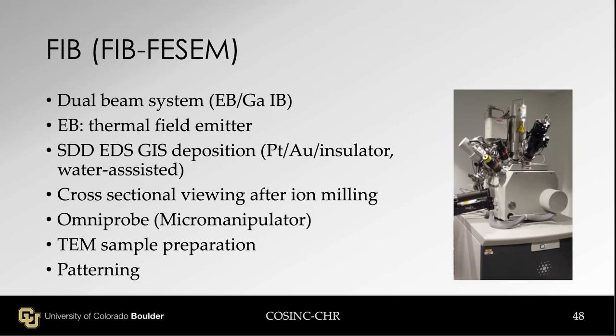Instrument looks like this. What we have is a dual beam system, electron beam and gallium ion beam system. Electron beam is a thermal field emitter. That means the field emission SEM. So it's better than tungsten filament SEM. EDS detector attached, and deposition. We can deposit platinum, gold, insulator, which is SiO2, and also water-assisted deposition is possible.